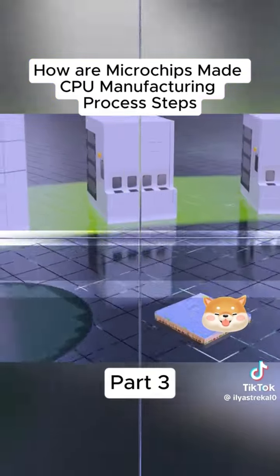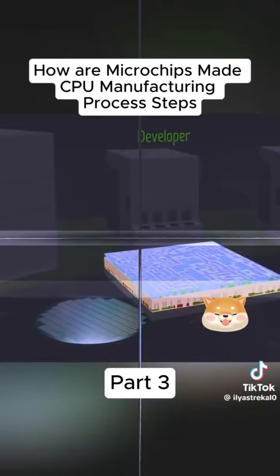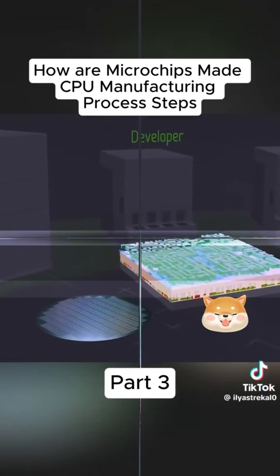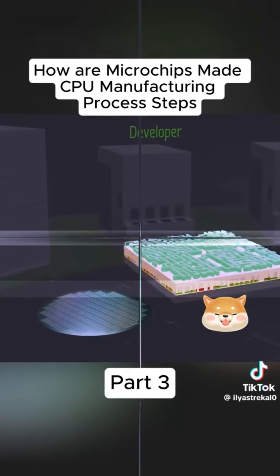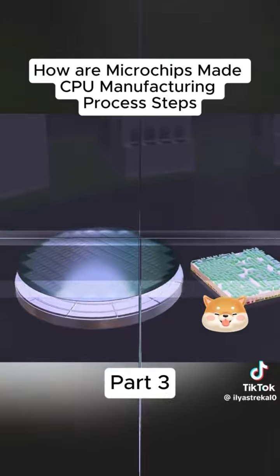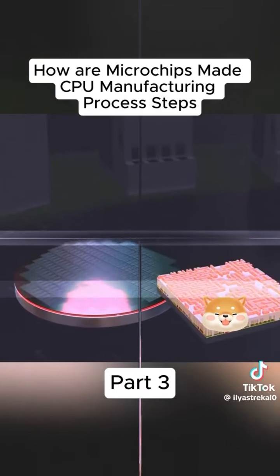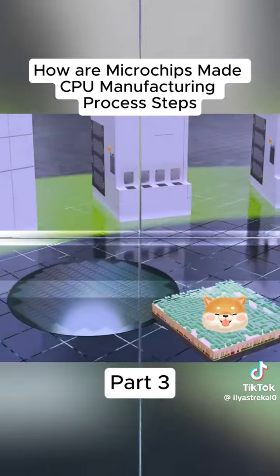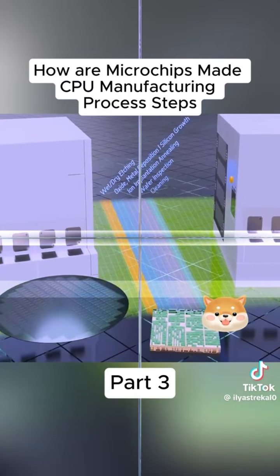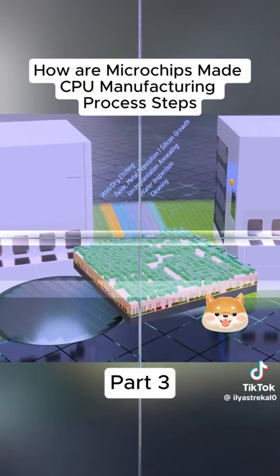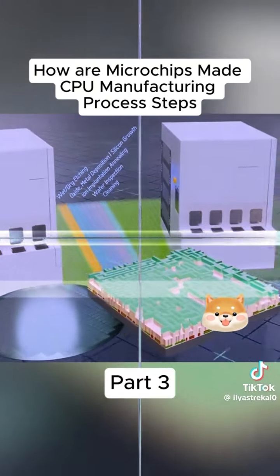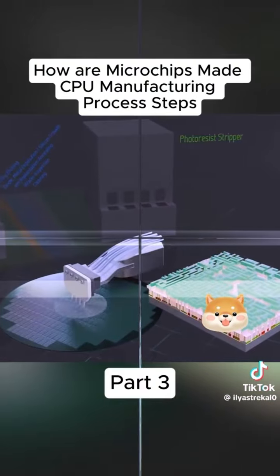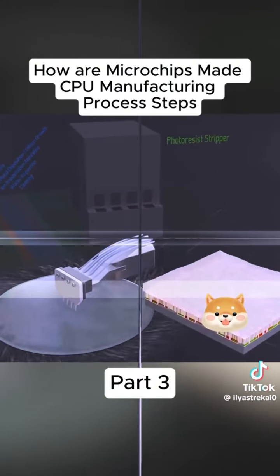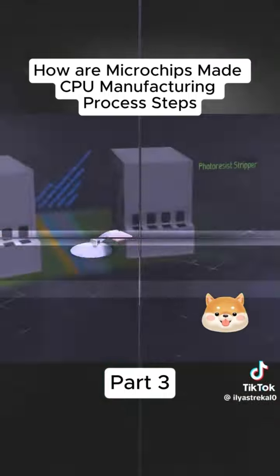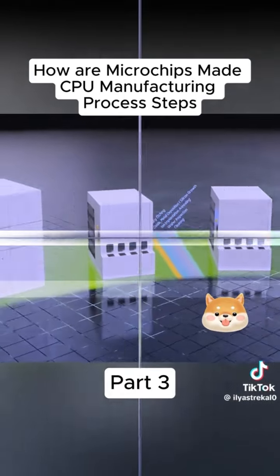The wafer then goes to the developer and the weakened photoresist is washed away, leaving only the patterned nanoscopic stencil on the wafer. The wafer is then sent through a hard bake to harden the remaining photoresist. Next, the wafer travels to other tools to undergo processing. And once these processes are completed, the wafer goes to a photoresist stripper, which uses solvents to dissolve and remove the photoresist mask layer. And that's how a mask layer is formed and then removed.